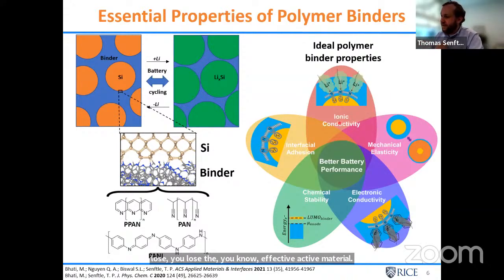The binder has to have good ionic conductivity. Lithium has to be able to get into and out of the material. It has to have a high elasticity because the particles are going to be expanding into the binder, so you don't want to confine the silicon too much so that it can't expand upon lithiation. Of course, it has to be chemically stable at whatever potential we're operating at. And there has to be some degree of electronic conductivity as well. So how do we use simulation to understand all of this?